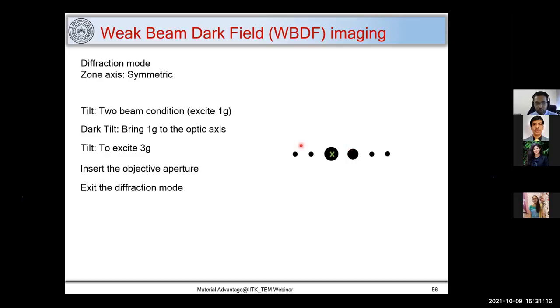Now what you do is dark tilt and bring the 1G spot to the optic axis. So I'm going to bring this spot to the optic axis. So I have brought this spot to the optic axis, and now I'll excite this 3G. So this is 1G, this is 2G, and this is 3G. So I excite that. I have made the intensity of this 3G spot more and the 1G spot less. And now I put an objective aperture and I image the dislocation. I come out of the diffraction. This is how I can get a weak beam dark field image.